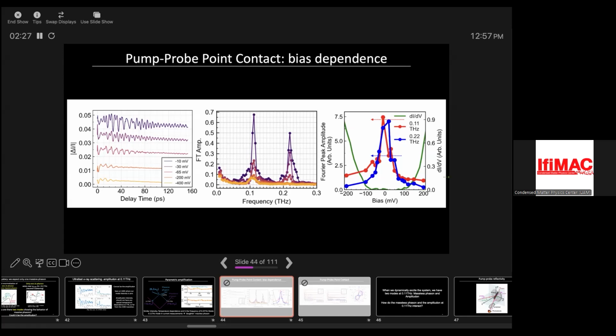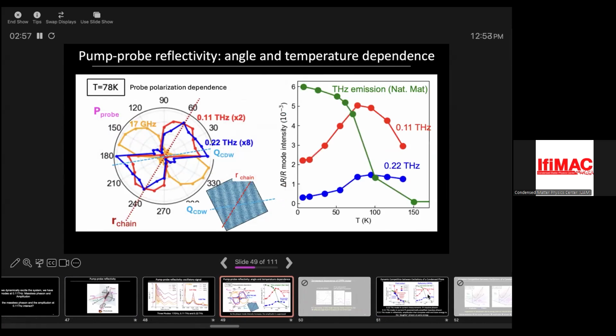Hi, thank you for your talk. When you do the reflectivity measurements, when you do pump probe, you discard the pump measurement by the polarization. But the thing is that when you couple different polarizations of light to a tip-sample system, they do not enhance in the same way, either by plasmonic enhancement or by confinement. So I'm not sure if rotating the polarization of the pump is going to affect your measurement. We've done both. This is the probe polarization rotation. We've also done the pump polarization, which has no features. So you rotate the pump polarization and it doesn't affect your result? No. But the probe does. Oh. Okay.